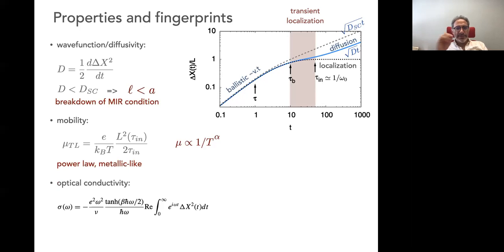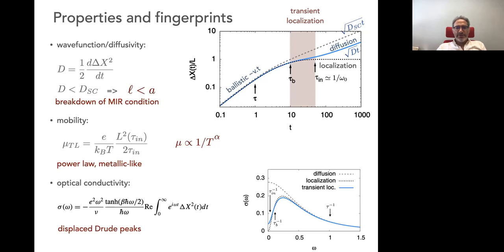And the third property, so this was, we were analyzing already at the beginning 10 years ago. There is this exact relationship that holds in semiconductors that relates this mean square displacement to the optical absorption. And I repeat, for independent electrons or holes, this is exact. So if you just Fourier transform these curves here and apply this detailed balance prefactor here, you can actually predict how the material absorbs light. Well, not the material, but the extra carriers that you have added and that are moving. And so I'm using the same symbols here. So the dashed here is for semi-classical transport, band transport, you get a Drude peak. This is well known in semiconductors and in metals.